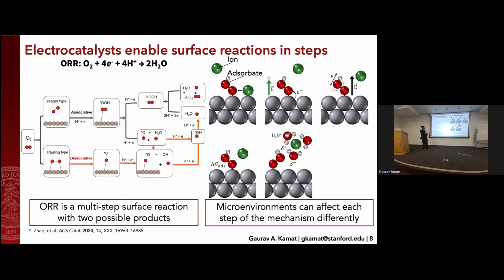And you also have effects such as pH buffering. Of course, any ion that's in your double layer or in your near catalyst region is going to be surrounded by water molecules just based on its hydration, and that can change the local pH in very unexpected ways. And lastly, there's some evidence that charges actually take very layered appearances in terms of stacking water and ion in order to balance the charge that's emanating from the surface.